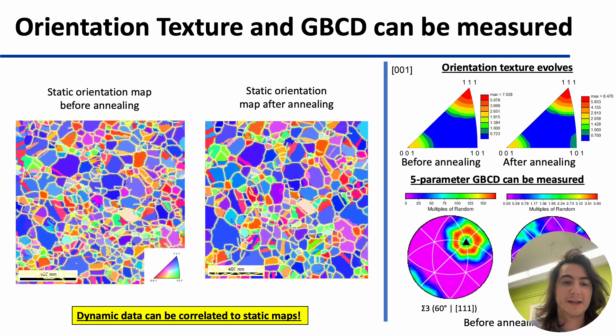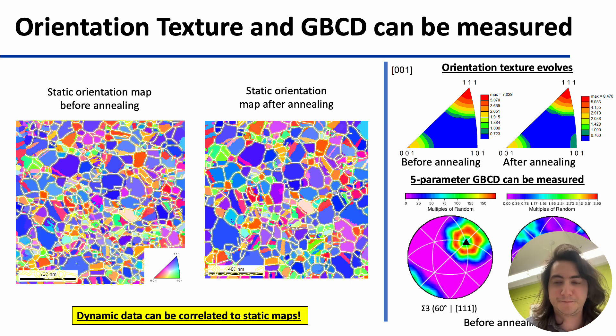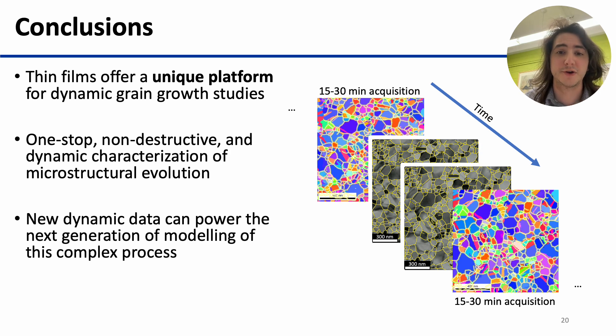Most importantly, we're able to do this non-destructively and periodically throughout annealing, in the same field of view on the same instrument during the same session, which means we can correlate our dynamic data directly to these static maps — meaning we can get dynamic information like grain boundary velocities or grain growth rates for a given grain, and correlate them back directly to the orientations measured before and after. This allows us to project crystallographic information like grain orientation and grain boundary character forward in time, carried as tags in the geometric data acquired in situ.